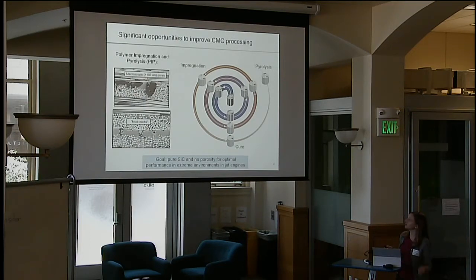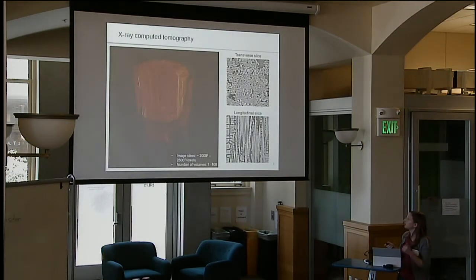So to do this analysis, we're using X-ray computed tomography. Here we capture 3D images of these materials in situ during processing, including both the fluid flow and during pyrolysis. A data set is shown here, rotating in 3D, of one of the specimens. Fibers are in the vertical direction, and here we have 2D slices showing what the 2D data looks like through this 3D image.